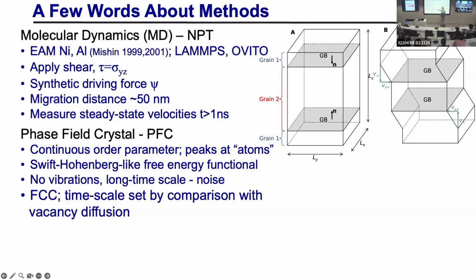And since there's no vibrations here, we can go to much longer time scales. What we're going to do is set the overall time scale in these kinds of simulations by matching the simulation results with how fast vacancies move. The point is, since you're not considering all the details of the atomic vibrations, I can't actually look at atom hopping. So it just sets a scale.